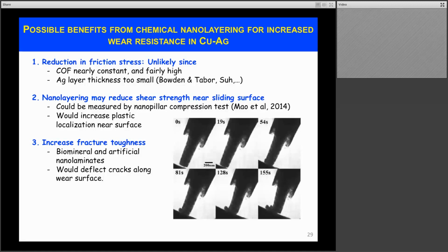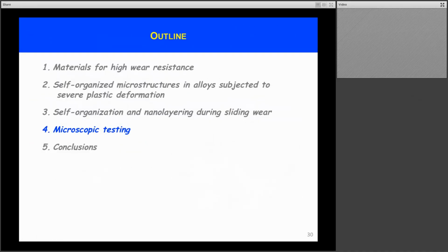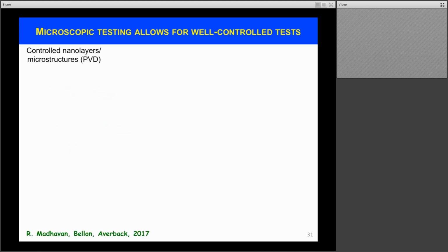And this nanolayer structure is in fact reminiscent to some extent of the nanolaminates that Alan Matthews mentioned in his webinar last month, or this Roman paved road, if you remember, where there are hard inclusions cemented together by a softer and more compliant phase, and this should promote fracture toughness. This understanding, however, is easier to achieve by performing microscopic testing. And so briefly in the remaining 3-4 minutes, I'd like to illustrate some of the results that we have obtained at Illinois using microscopic testing.